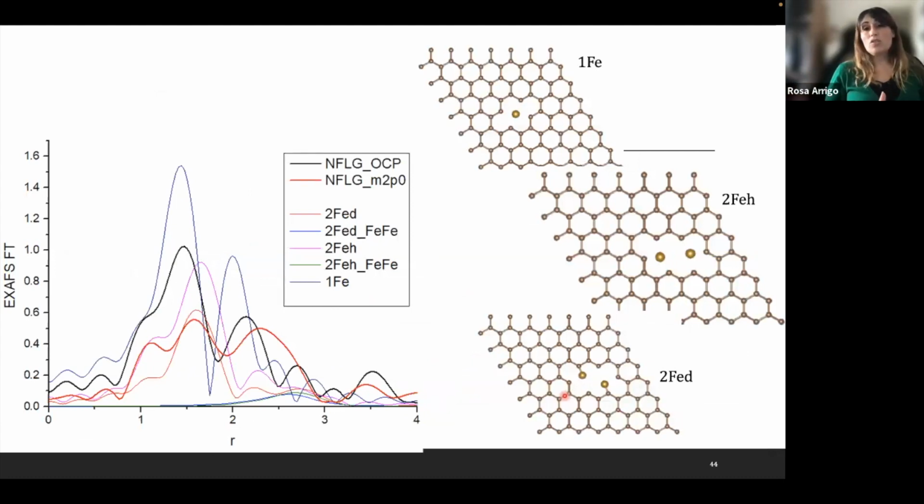Anyway, we also try to see whether changing the distance arbitrarily, because this will clearly show that we may need a more advanced approach to this analysis, because you can see here that the starting material at open circuit potential can be described mainly by this iron site in the vacancies, more or less, but not completely, and particularly not completely at this higher distance. And this higher distance actually increases upon CO2 reduction.